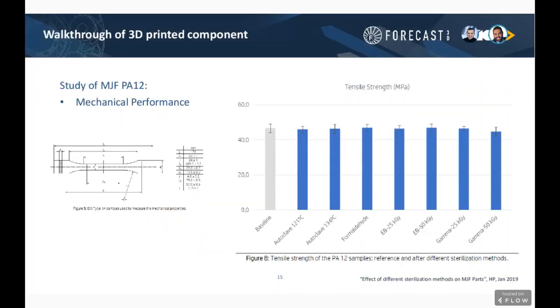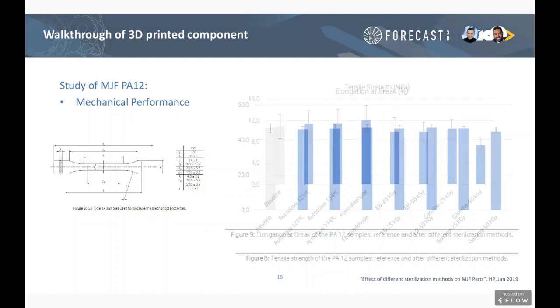So that data point exists. There's electron beam testing at different power levels, and then gamma radiation. So depending on what method you're going through, the results will change, and you can see how they change from the baseline here. On average, the tensile strength remained fairly similar for their PA12 product. If we go to the next one, it's evaluating the elongation at break. You see a little bit more variation with what the processes are doing to the base material.